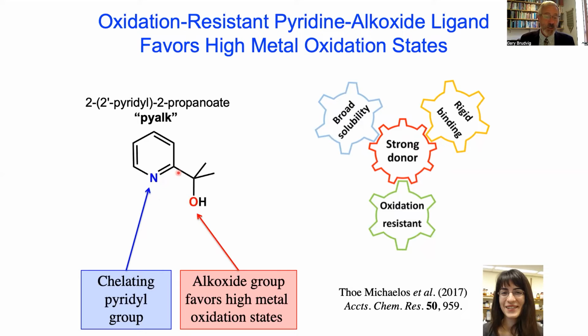It combines chelating stability with the hydroxyl group of the alcohol, which can deprotonate to facilitate proton-coupled electron transfer chemistry. And also in the deprotonated form, the alkoxide very strongly favors the high oxidation states of metal ions, which are necessary to achieve in order to catalyze the oxidation of water. And we wrote a review article on this to describe some of the applications.